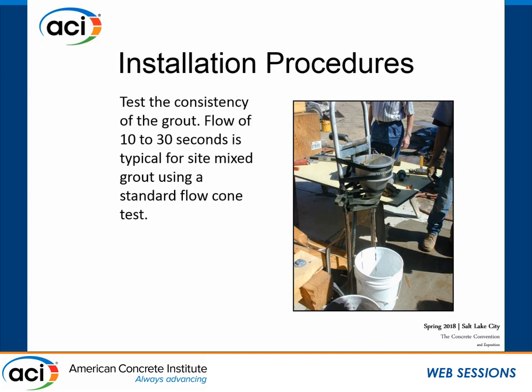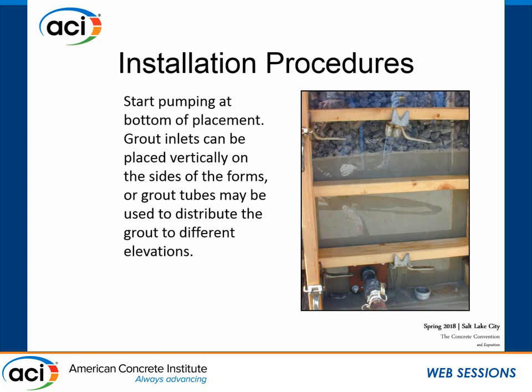The grout is typically tested with a flow cone — you're looking for a flow of 10 to 30 seconds for site-mixed grout. You install an inlet at the bottom and either pump from just the bottom for small applications, or use numerous inlets working upward as you do with epoxy injection. You inject at the bottom, and when it reaches a certain height, close off the bottom, install your hose at the next level, and move up. Alternatively, you can have numerous grout tubes embedded sacrificially in the mix and just keep working your way up.